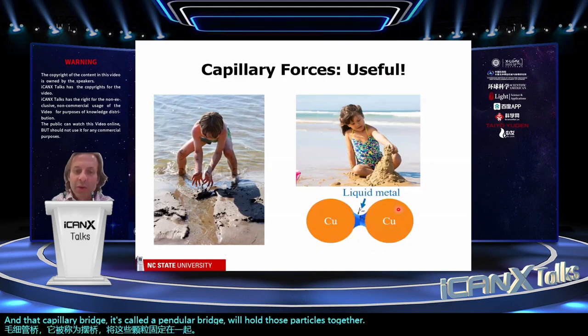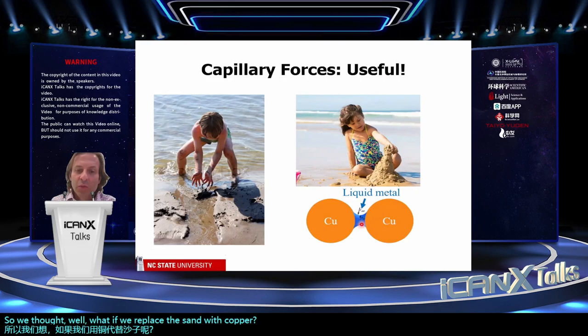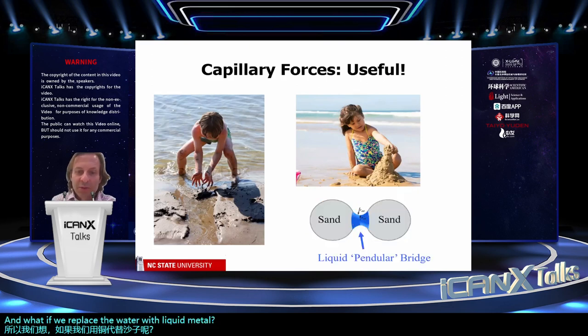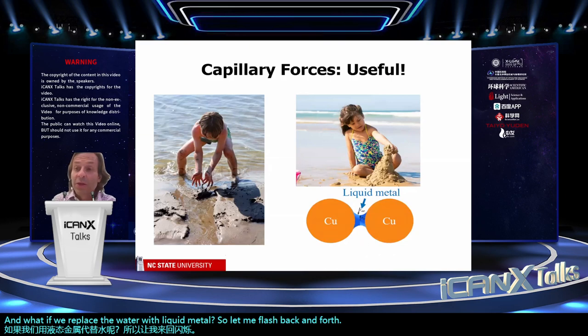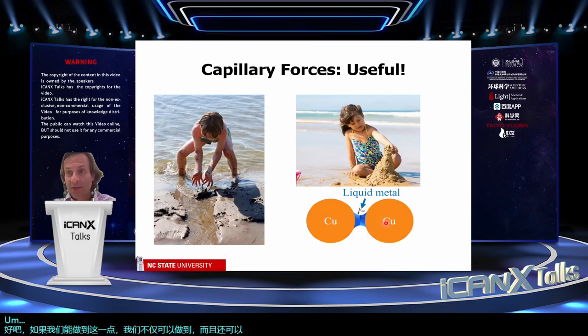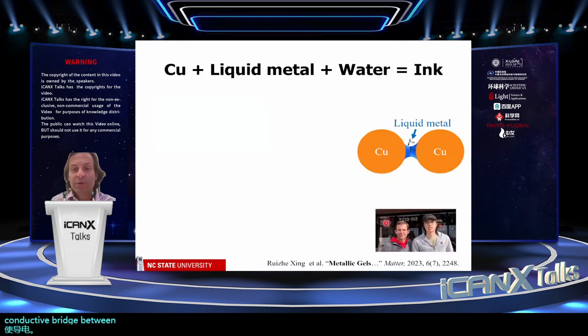So we thought, well, what if we replace the sand with copper? And what if we replace the water with liquid metal? So let me flash back and forth. Okay, so if we could do that, not only can we make a paste, but we could also make a conductive bridge between the particles.